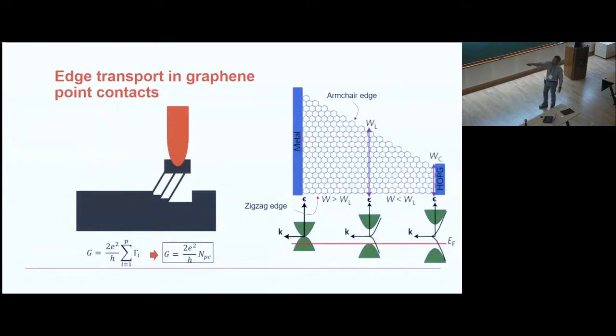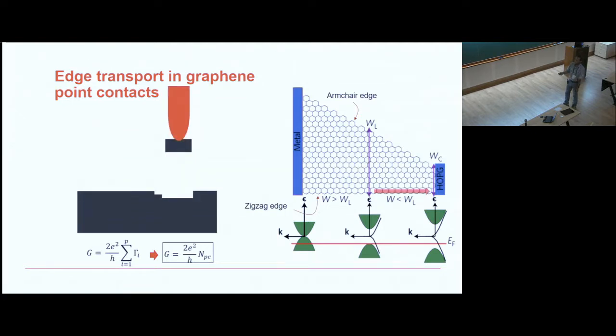So this is a taper of the edges. Each of them essentially have this kind of structure. At very large, in this region, these are the bulk bands. The Fermi energy is sitting in the bulk. So this region essentially is acting as a lead, whereas the actual edge current flows somewhere here. And this was recognized by our theoretical colleagues. And when the Fermi energy is in the bulk gap, in between the bulk bands, the only conducting state is along the edge. Now, why there are multiple steps is because as you take the tip out, you start rupturing one after the other and essentially leading to stepwise behavior, which is quantized in a universal manner.